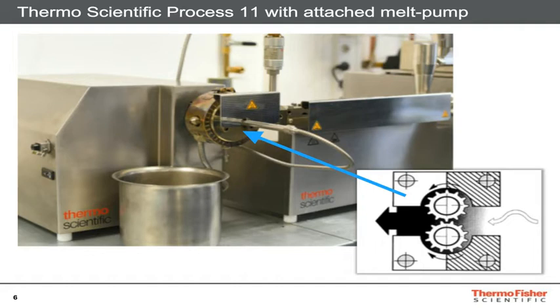The melt pump uses two closely meshing gears that rotate and then separate on the inlet side of the pump. We see a small picture on the down right side here. This creates a cavity and a suction that is filled by the melt coming from the extruder. The melt is then transported by the gears to the outlet side of the pump, where the meshing of the gears displaces the melt. Since the mechanical distance is very, very small, the melt is effectively prevented from leaking backwards. The rugged construction of the gears and the housing allows high pressures up to 700 bar, and thus the ability to pump highly viscous melts. And by controlling the speed of the melt pump, a very accurate pulsation-free output can be maintained, resulting in a tight tolerance on the millimeter diameter.